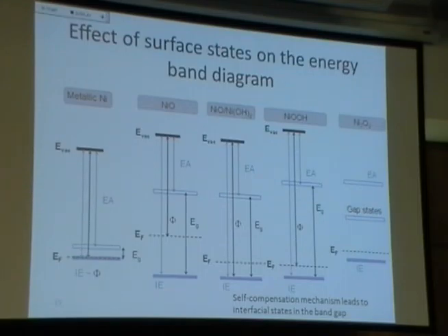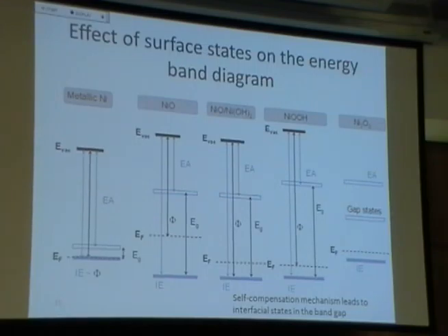Well, what's interesting about these is that if you go through the spectroscopy of the two, the oxyhydroxide gives you this p-type that you want, and then you actually get an increase in your optical band, or in your electric band gap. Alright, and this has to do with the dipoles that are happening on the surface. Conversely, when we dope nickel oxide extensively with Ni2O3, what we actually get is these unwanted gap states. And look where they appear.